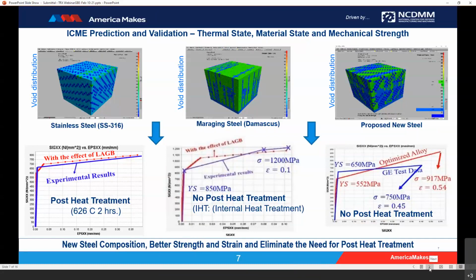It should be noted that the heat treatment for SS-316 stainless steel improved the strain, but only had a slight improvement of strength. In the case of maraging steel, the inherent heat treatment improved the microstructure and increased the strength, but not the strain. Preliminary investigation with the optimized alloy resulted in an increased strength and an increased strain without heat treatment. The results need to be validated against tests, but the research clearly is moving in the right direction.